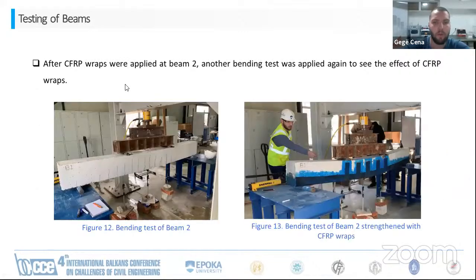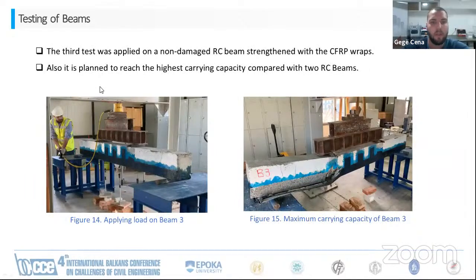wraps. So this is beam 2 after CFRP wraps were applied, and another bending test was applied again to see the effect of CFRP wraps. So this is the first bending. This is the second bending of the same beam. The third test was applied on a non-damaged reinforced concrete beam, strengthened with CFRP wraps. Also, it was planned that this beam would reach the highest carrying capacity compared with the two reinforced concrete beams. So these are the pictures from testing beam 3.